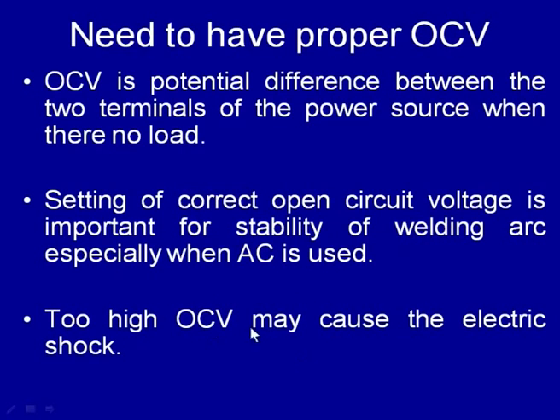When AC current is used, the magnitude and the direction continuously change during welding, and under these conditions the arc will have the tendency to get extinguished if a high open circuit voltage is not used. But too high an open circuit voltage, like 100 volts, may give an electric shock while working. So, it is not desirable to use too high an open circuit voltage, but setting the optimum open circuit voltage is important for stabilizing the arc and to initiate it easily during